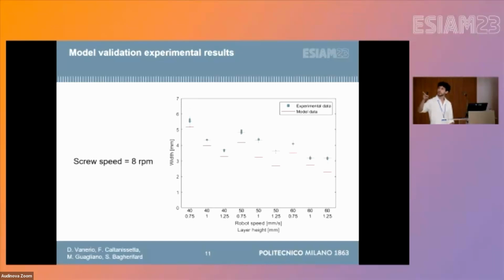In this case, you see 8 RPM, so we have an increase, as expected, in the average width, but still an underestimation. The same holds for the screw speed of 9 RPM. In this case, we can also notice that the first value, 40 millimeters per second robot speed and 0.75 millimeters layer height, appears much wider. I mean, the box is much wider than the others. This is because this is also a limit condition in which the process is not completely stable, because we have too much material for the speed of the robot and for the layer height.